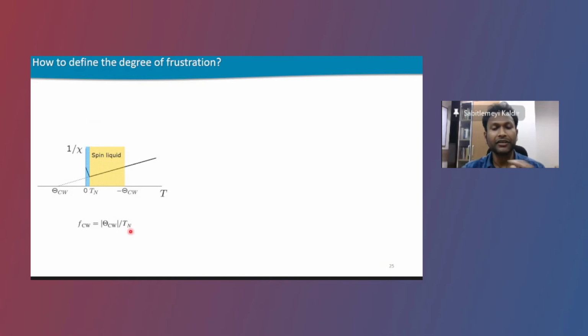Usually in a normal unfrustrated system, you would expect that these would be similar in magnitude. But in the case of a frustrated system, the exchange interaction is much larger, but the system is unable to go to a long range magnetically ordered state because of the effect of the frustration. The ordered state comes at a much lower temperature. So the larger the difference between the Curie-Weiss theta and the ordering temperature, the more degree of frustration. That particular definition was very well celebrated in the case of insulators.